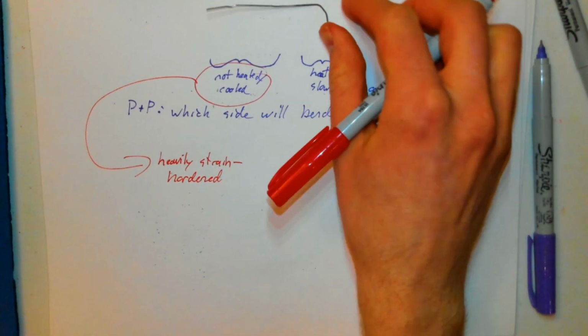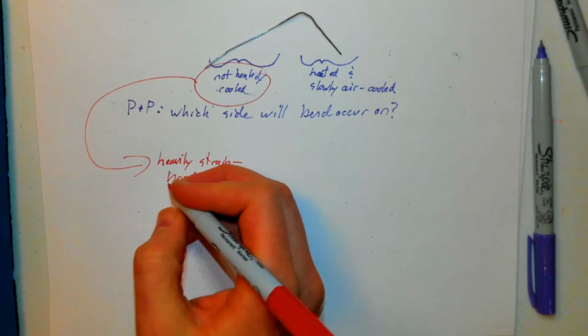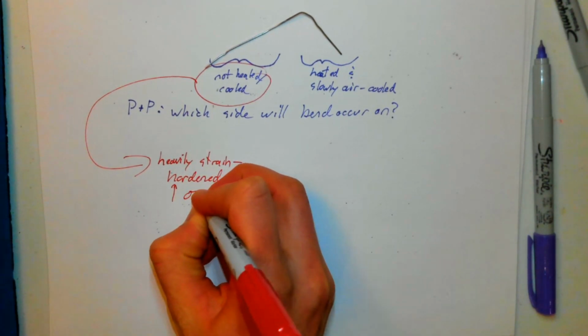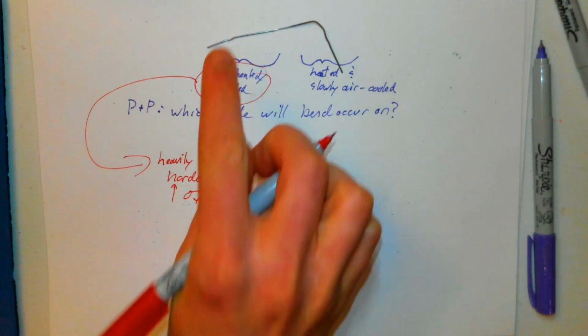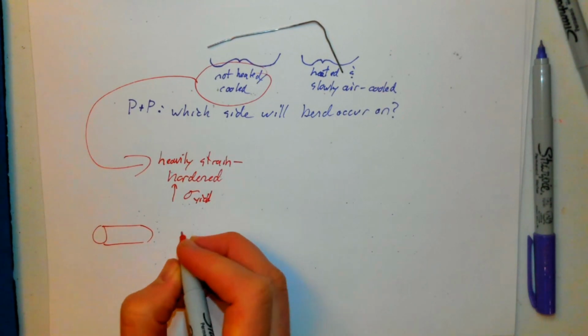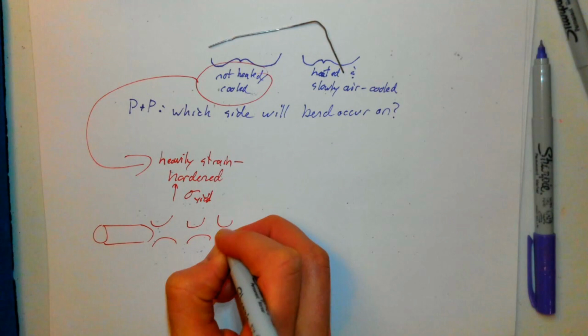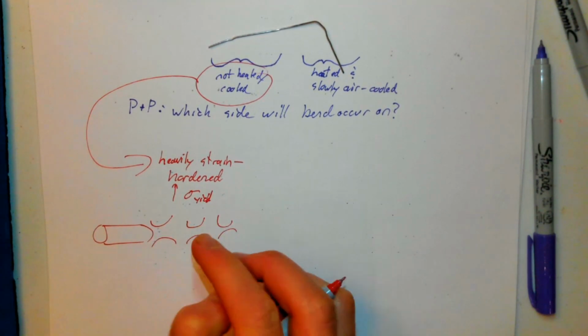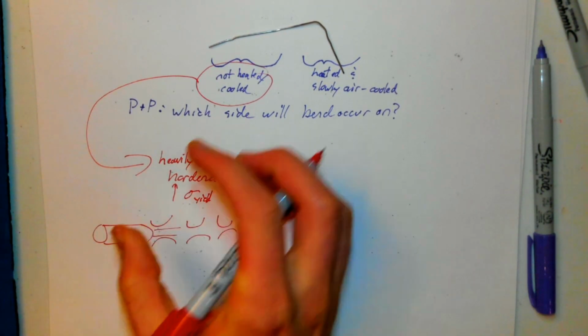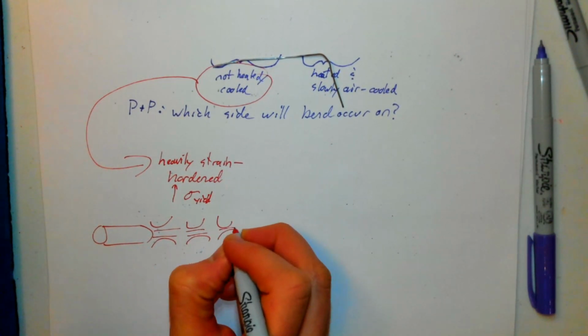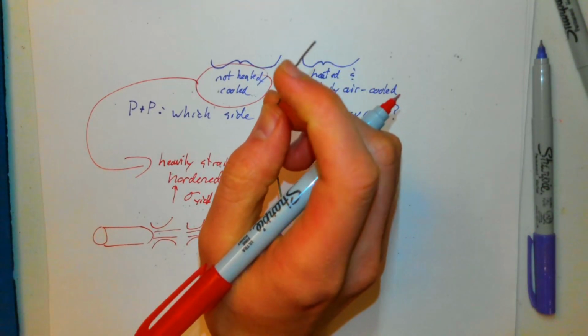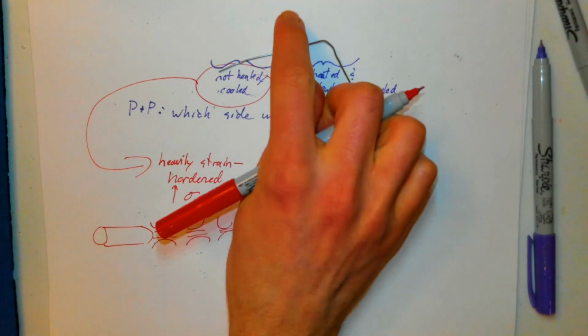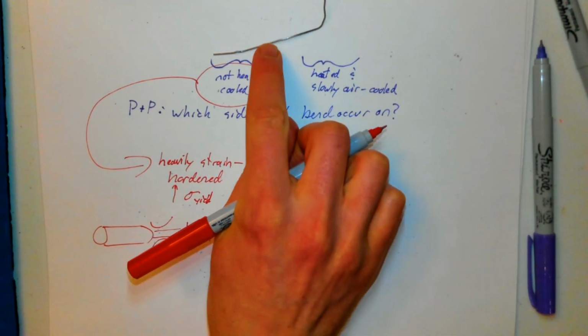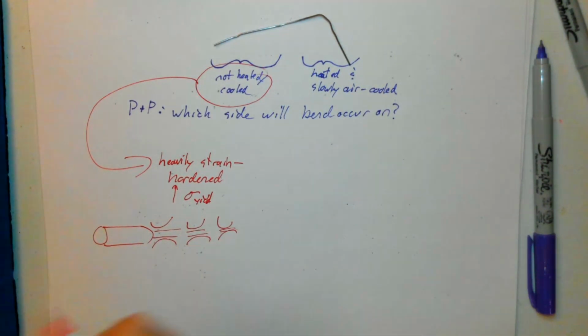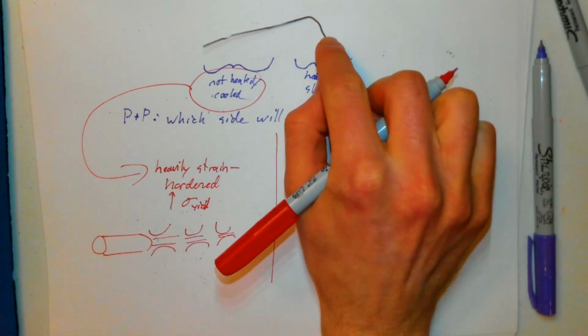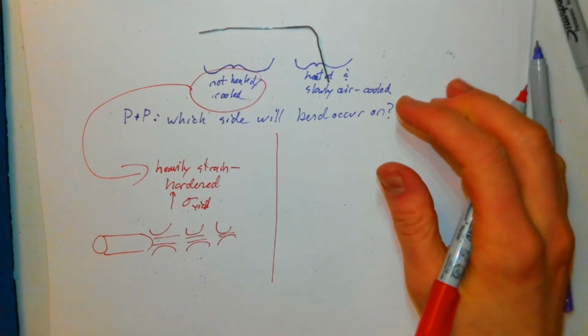And when that steel was heavily strain hardened, it basically increased its yield strength. The way they made this steel wire, they started with a very large cylinder, and then put it through a bunch of successive smaller and smaller rollers / stretchers that turned what was a cylinder like this into smaller and smaller cylinders, eventually bringing it all the way down to this wire. So the left side was heavily strain hardened, which increased the yield strength of the steel on this side, but all of that strain hardening was undone when I heated and slowly air cooled this right hand side.